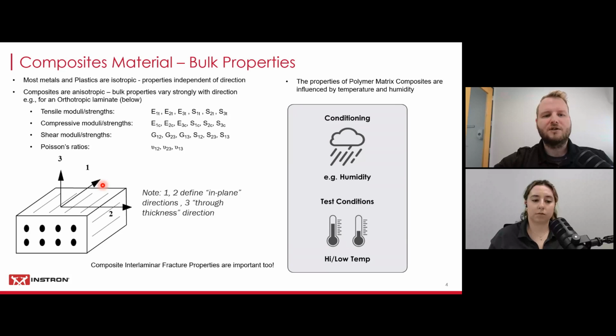Composites, on the other hand, are considered anisotropic, which means that the bulk properties vary strongly with the direction that a load is applied. So if we take this example down here, and you see these black dots and these lines go through, they're all supposed to be those reinforcements we saw on the previous slide, all oriented towards direction number 1. So if you were to apply a tension or compression load in direction number 1, the material would be very, very strong, because all of these fibers are there to take up that load.